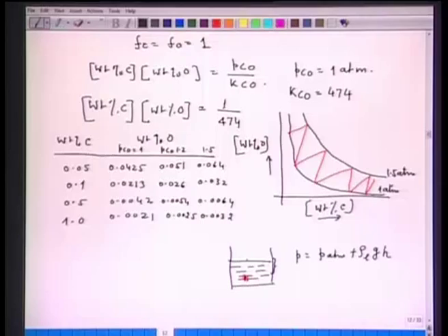Now, in another situation, if the nucleating site is here, at the slag, that is, at the slag metal interface, then we can consider the nucleating bubble will be experiencing only atmospheric pressure, for example, equal to 1 atmosphere. So, depending on where the CO bubble is nucleating, the dissolved oxygen in steel may vary.